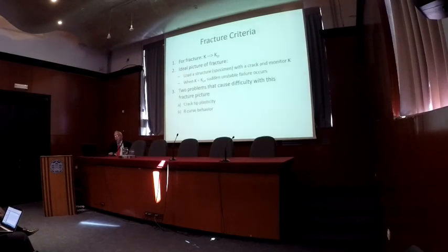So, talk a little bit about fracture criteria, and this is a kind of a side thing, but it's an important consideration, which is this, that ideally, you would think, here's the way to get fracture. For a body, you can calculate the K. You have the handbook or you have other solutions. So if you know the K for the structure and you know a critical value of K, and we'll talk about what is critical values of K later, then when your K reaches its critical value, you get failure.